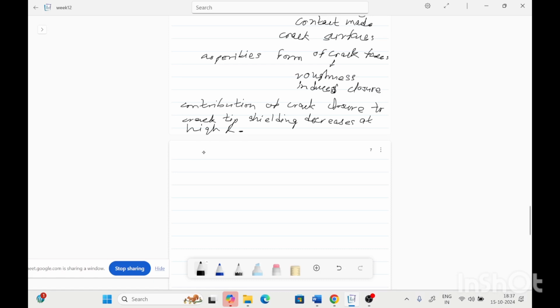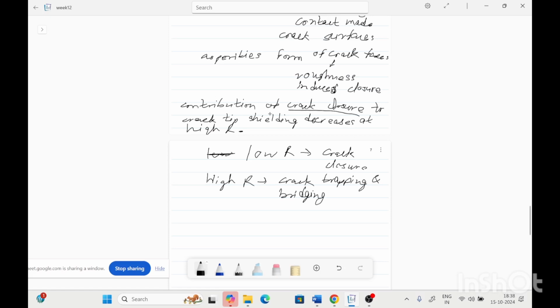So for the low R value, the crack shielding will generally be done by the crack closure, and for high stress ratio, the crack trapping and bridging will happen. Means it depends on the stress ratio value. So if the R value changes, the phenomena for the crack growth rate will change.